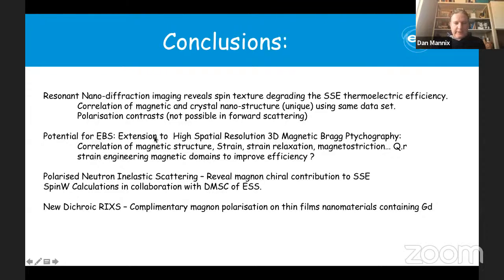We've got this potential use of EBS, but we hope that we can try to develop some kind of high spatial resolution 3D magnetic ptychography, correlating again magnetic structure and strain effects also in 3D. We used polarised neutron inelastic scattering to get a lot of information on the magnon properties of these materials. And what we've done recently is try to complement that with thin films using circular polarized RIXS to get information possibly on the polarization of the magnons too.